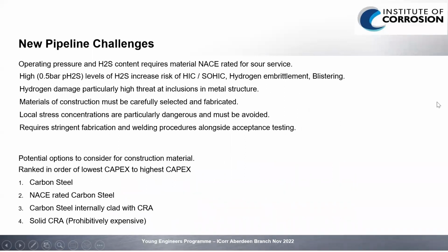So the main challenge with this new pipeline is, like I say, it's a sour reservoir. We've got 50 ppm H2S, and with our operating pressure, it puts us into the sour service area. So that's going to increase our risk of all the hydrogen damage mechanisms: hydrogen cracking, stress-oriented hydrogen cracking, sulfide stress cracking, even embrittlement, blistering, all of that. And because of the localized and aggressive nature of some of these, we could end up with a loss of containment, which obviously we have to avoid at all costs.